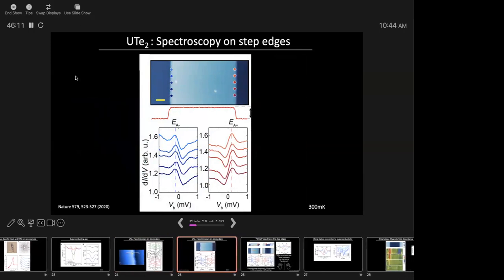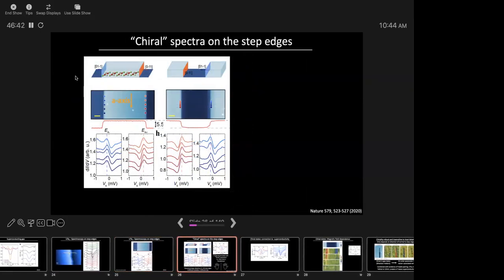Also, the way you think about this is a terrace. There's a step up on this side and then a step down on this side. If you go to the step down, then you see the peak above the Fermi energy. You go to the step up on this side, you see the peak below the Fermi energy. So basically, the position of the peak with respect to the Fermi energy is sensitive to the direction of the normal to the step edge. So this is the a-axis, by the way. If you go to this trench, it's the same thing. The direction of the normal to this step edge is to the right, and therefore you have a peak above the Fermi energy. The direction of the normal on this step edge is to the left, so you have a peak below the Fermi energy. Now there are a lot of problems with this.